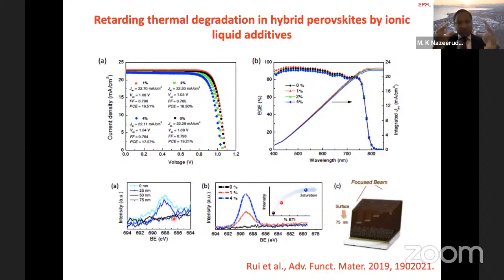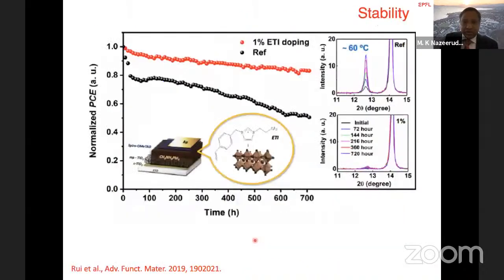When we have this 1% of ionic liquid in the perovskite, because of the solvent, the ionic liquid is floating on top of the perovskite. And when the perovskite is forming the crystals, it is forming a shell around the perovskite grains, as shown from this data. The stability is significantly enhanced compared to without ionic liquid.